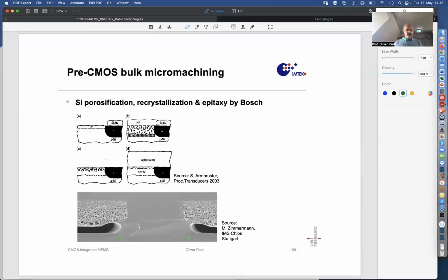So in this case, what you see here is a starting structure, a crappy picture from the original publication, which says N. Does it say N? I thought it was P plus. Yeah, this should be P plus, and then there is P silicon below. So let's make this P plus, and this is P. And then here we have some N structure, N silicon, which is also covered by silicon nitride. So by exposing that wafer to hydrofluoric acid under a given etch condition, what will happen is that there will be a fine-grained porosification at the surface, and then a rougher porosification in the P region because of this dopant dependence. So you see the result here on the side.